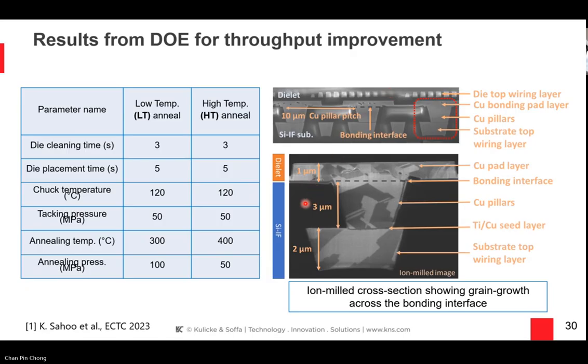And you can see here in these cross sections, the bond line is actually where the dashed line is. And what you're seeing there is in this case a 3 micron pillar that is jutting out slightly above the surface, and that bonds to the pad which is on the top. And you can see the beautiful grain growth. There's very little remnants of voids. I mean, if you look very, very carefully, there'll be one or two voids, but they're far away from the interface. And this is a typical cross-section that we get. So if you send us a wafer, we'll bond it for you, and you will get pretty much the same results. Okay, next chart.